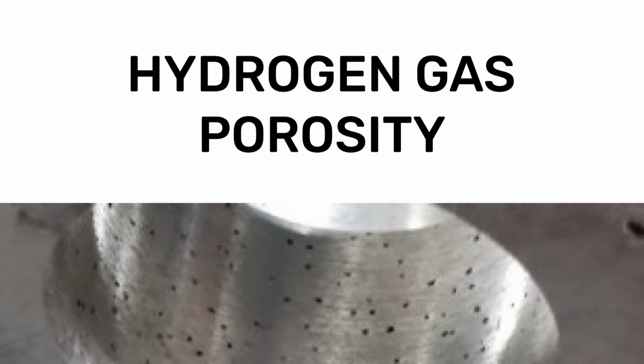Now, this type of gas hole porosity we've been talking about shouldn't be confused with hydrogen gas porosity. Hydrogen gas porosity is a whole different thing. Hydrogen gas porosity also appears as these smooth round holes, but the difference is that it appears throughout the entire casting. It's not localized. It's an internal porosity, so you won't really notice it until you break the surface of the casting.